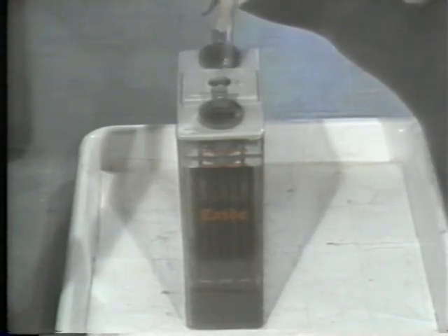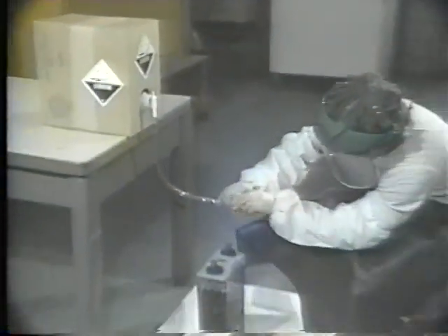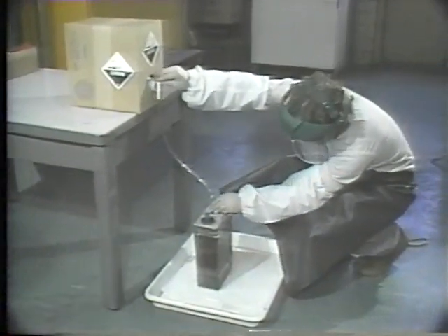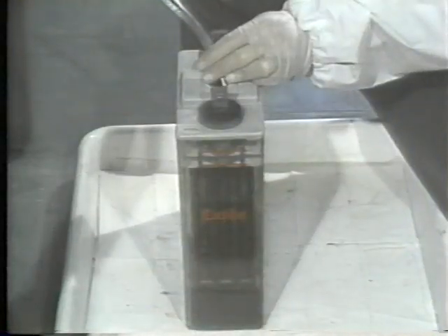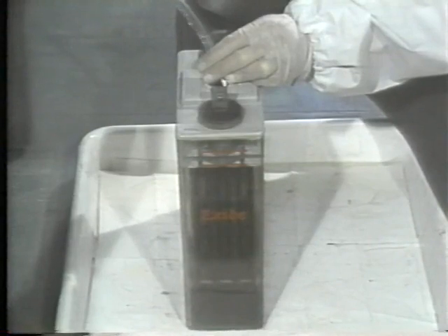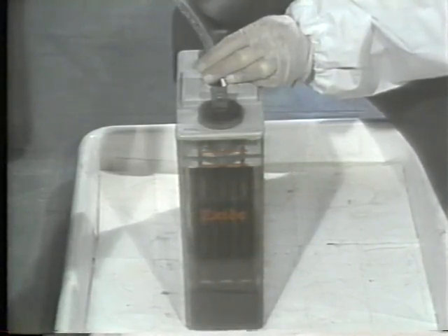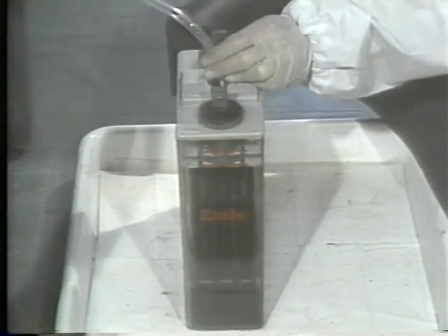This waiting period allows the electrolyte time to soak into the pores of the positive and negative plates. When the waiting period is up, the level is checked once again. The electrolyte level is slightly lower now, since some of it has had time to soak into the plates. To make up the difference, he adds electrolyte, not water. Adding water now would dilute the electrolyte beyond the recommended specific gravity.